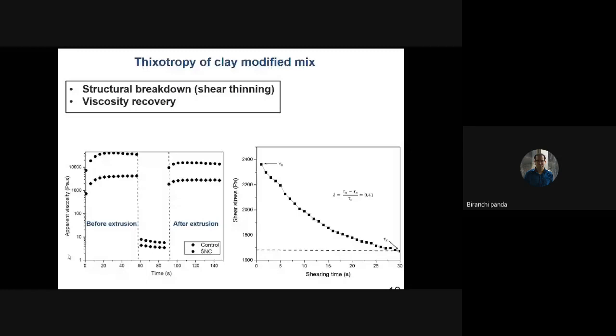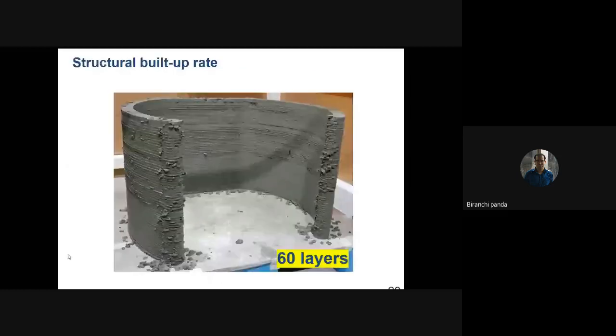So it is still well and good for our applications. We can deposit the material without having the behavior of flowability, because during extrusion the material completely loses its viscosity, but after extrusion it can recover its viscosity, and with this high viscosity we can print layers without any deformation. So whatever material we developed, we have printed more than 60 layers, and this is a very tall structure that we printed for one of our projects. That project I am going to show at the end of my slides. So this is all about material development.